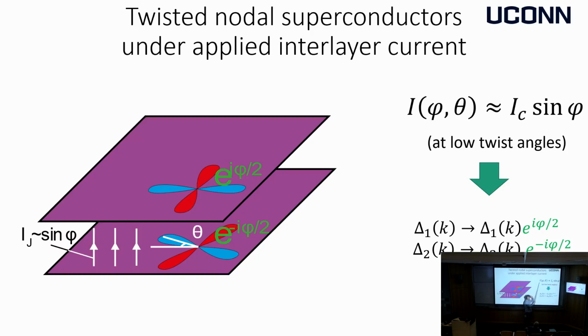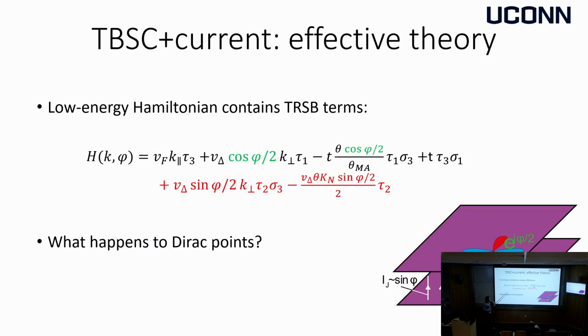I will say, let's drive a current through the system. Less than the critical current is going to generate a phase difference. That's it. I'm going to introduce the phase difference by hand. What this does to me is this continuum Hamiltonian I just derived acquires a couple of new terms. And most important of these terms, which, as you can see, vanishes for both zero twist and zero phase difference, is a term that has an imaginary component and that corresponds to a superconducting order.